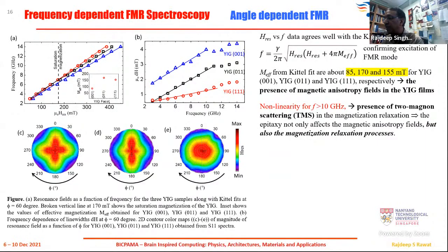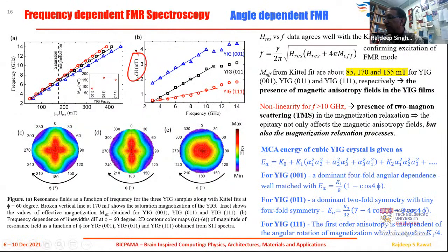Another thing to notice here, for the ΔH measurements, is that after the 10 gigahertz range the data is nonlinear. You cannot fit it using a linear fit. This observation tells you that we have what we call 2-magnon scattering. It is well cited in the literature that when you see that nonlinearity in your ΔH versus frequency curve, it is a clear hint of 2-magnon scattering being present in the system.